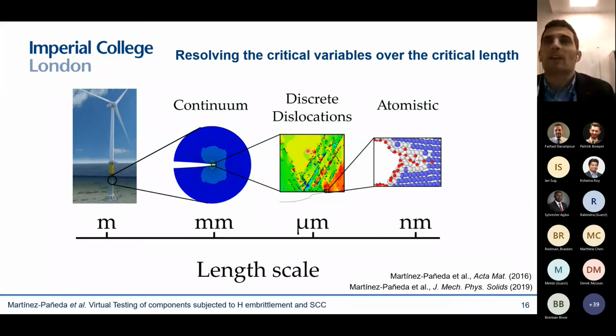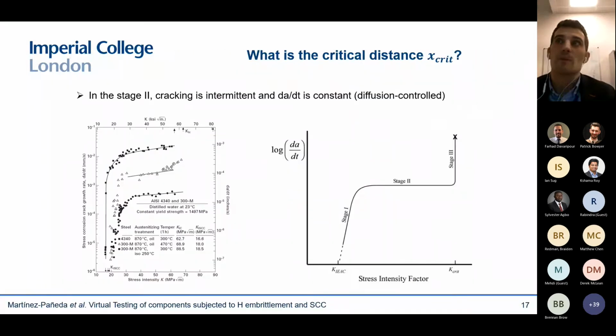So what is the critical distance for hydrogen-assisted fracture? Well, we know the critical variables, that is hydrogen concentration and the stresses. Let's figure out the critical distance. And we can do so from experiments. There are multiple ways we can do so, but one of them, I think that is quite visual, is from experiments. So if you do a fracture experiment with hydrogen, you'll get a response like this. So this is crack speed versus stress intensity factor or crack tip load, so to say, right? So you can see that there are 3 stages.